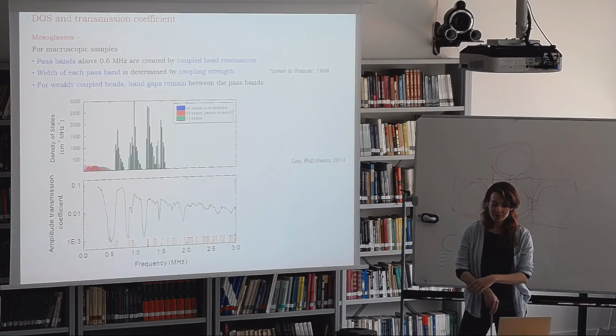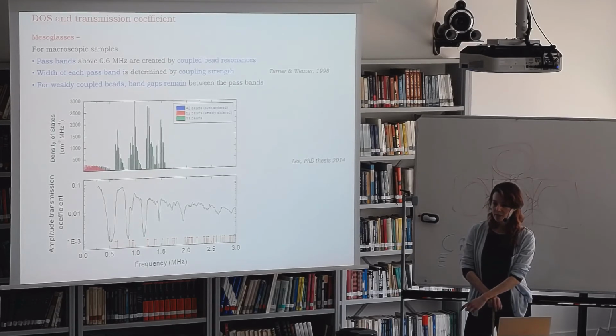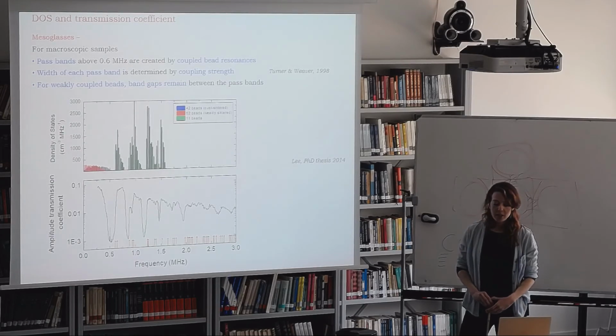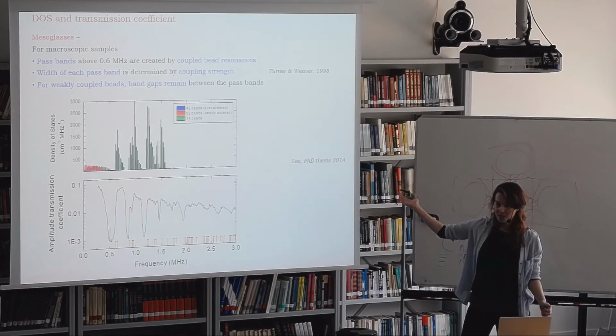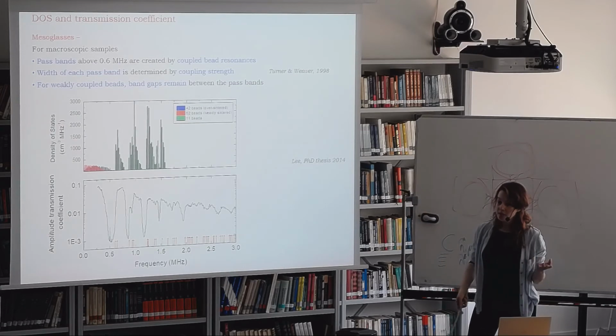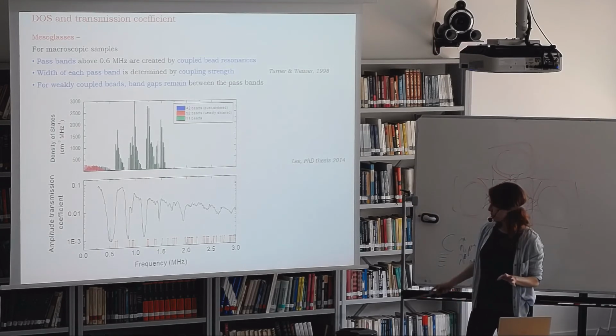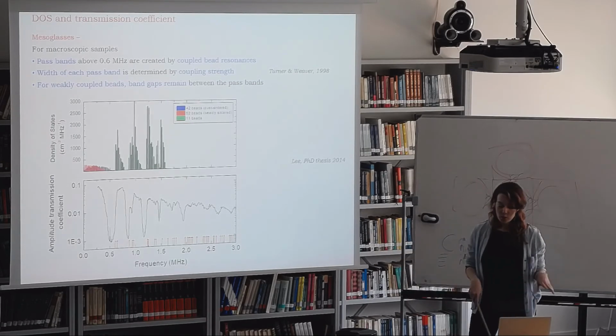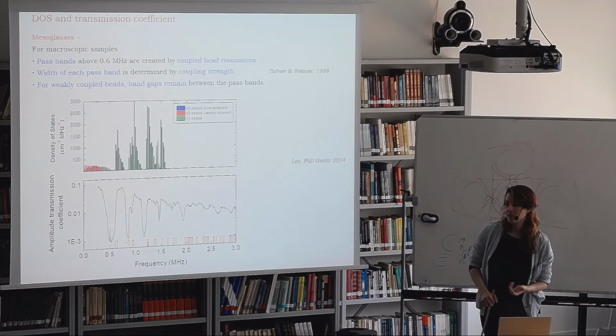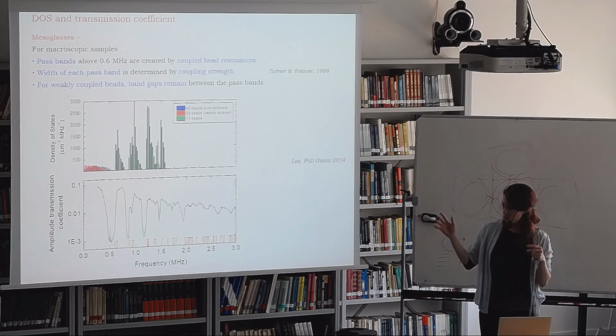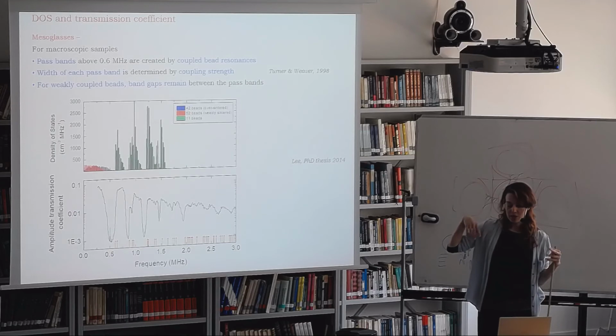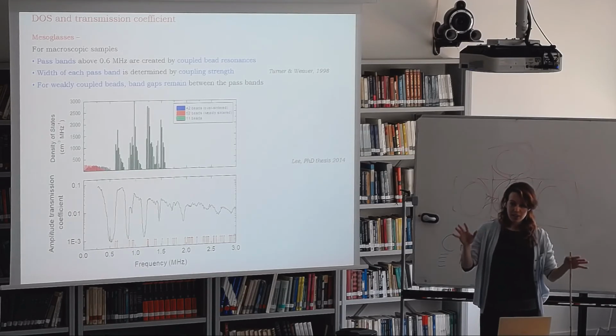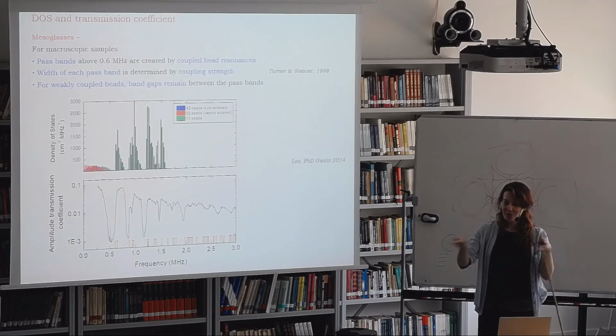So for the Anderson localization, were you expecting to have a band of frequency or only one frequency for the transition? It had never been observed before, but it is logical because at way higher frequencies you also see diffusion again. And so the initial experiments had not observed the second phase transition because, since they were performed in this band gap, there just wasn't enough signal. But it makes sense because localization occurs when you have very strong scattering. And for classical waves, this occurs only in this intermediate frequency regime, which we saw way at the beginning. So at lower frequencies you have diffusion, and then at higher frequencies you also have diffusion. So it makes sense to have two transitions into localization.